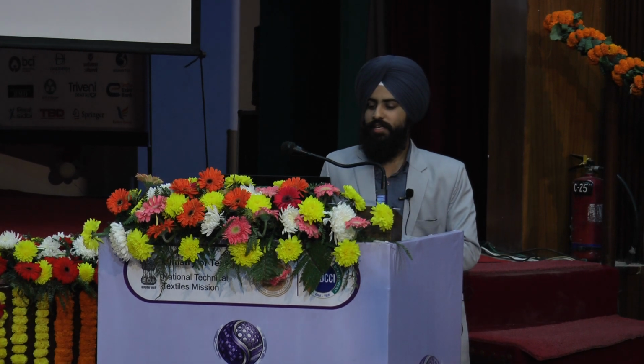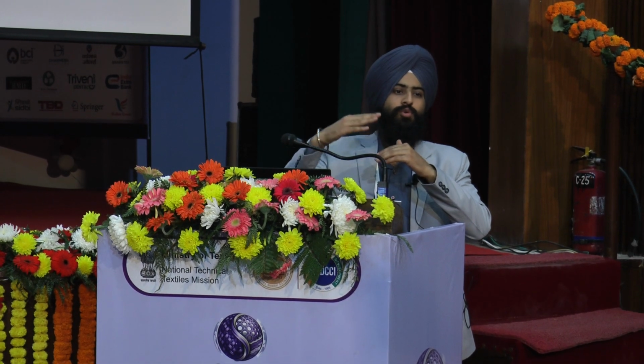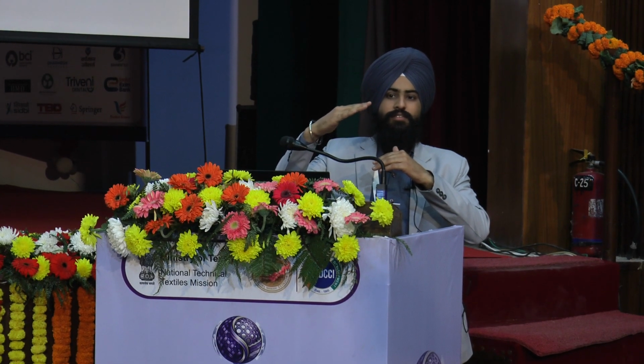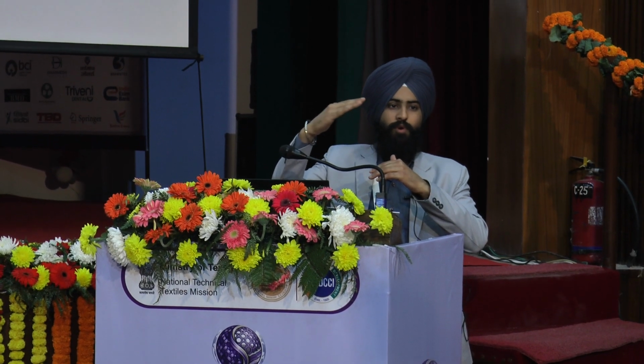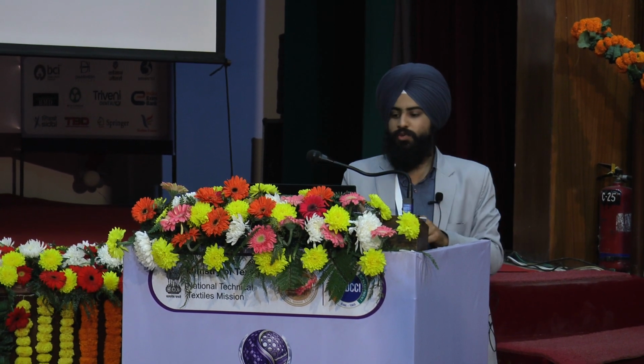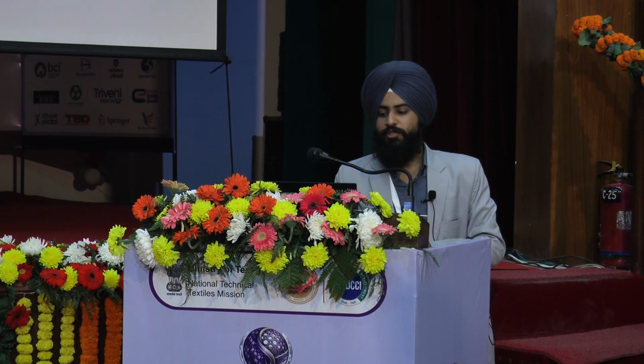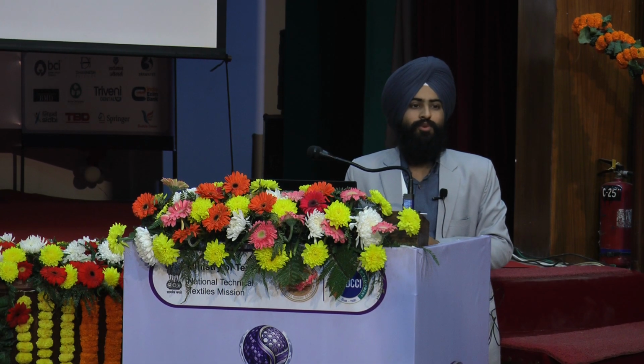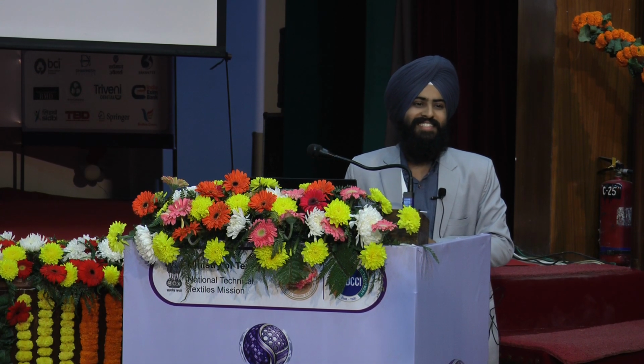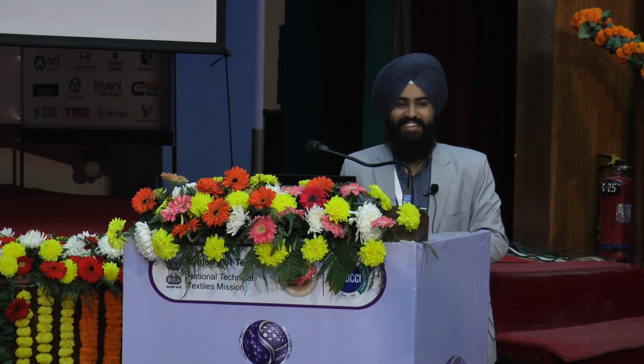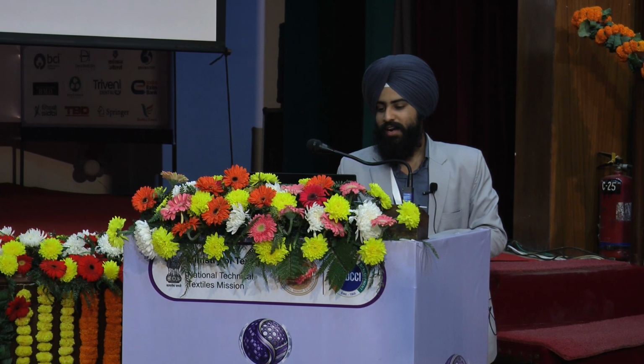While in the flexural test, in bending, interfacial strength still holds some importance, while the load is being taken by the metal faces and the core. So that's why the flexural response is almost similar for all four sectors. Flexural strength and flexural stiffness are practically similar. So we'll try to analyze the fatigue.